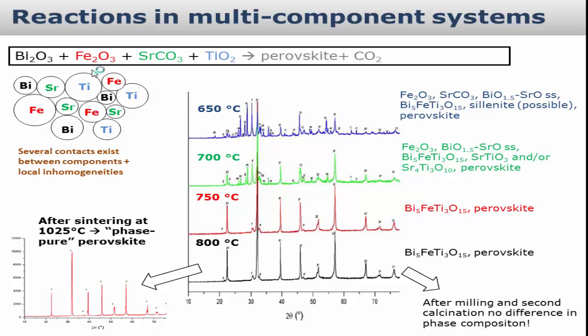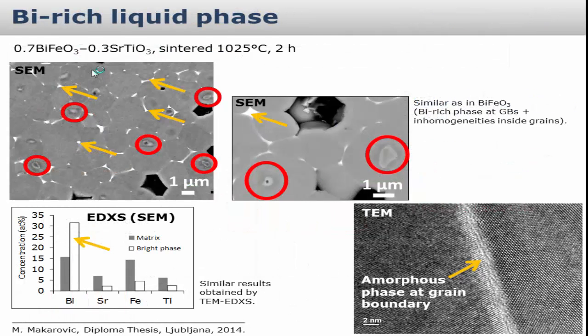Well, the message I want to tell here is that this is sometimes very dangerous. One cannot ignore all these phases that are formed when you heat the material at a certain temperature, especially in bismuth ferrite, and I would also say generally in bismuth-related materials. They tend to form these bismuth-rich phases with usually very low melting temperatures.